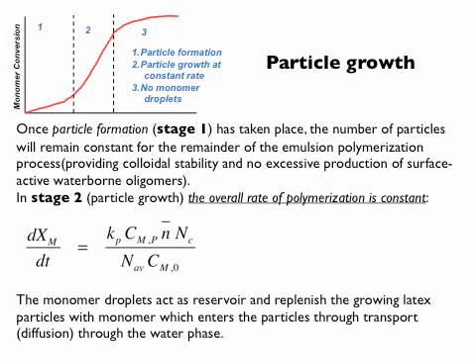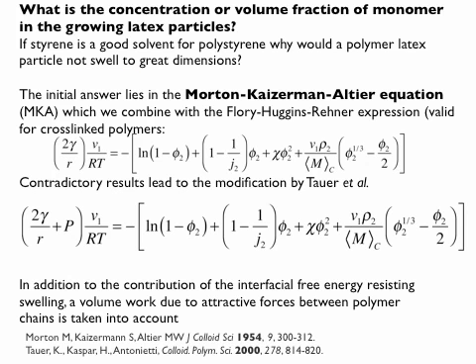The radical flux in most reactions is relatively constant, and that's why you end up with that straight line. Then in stage three, the monomer droplets are gone, so the rate of polymerization drops because now the monomer is consumed in the particle and transferred from the water phase, but there are no monomer droplets anymore — so slowly but surely all monomer concentrations drop in all phases. This is a good point to stop, as the equation needs more time to understand properly. We'll continue on Monday.